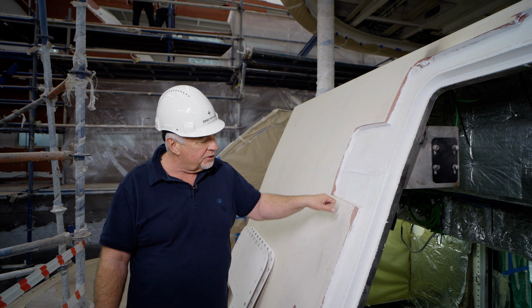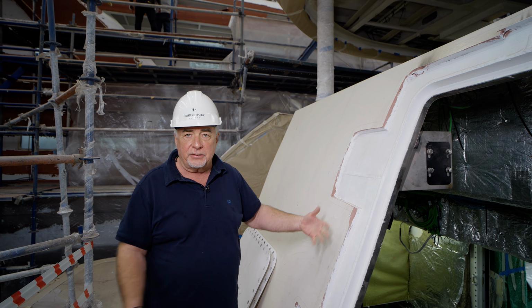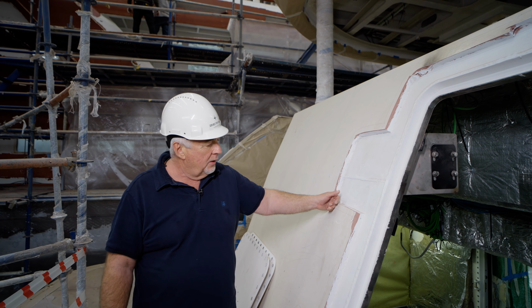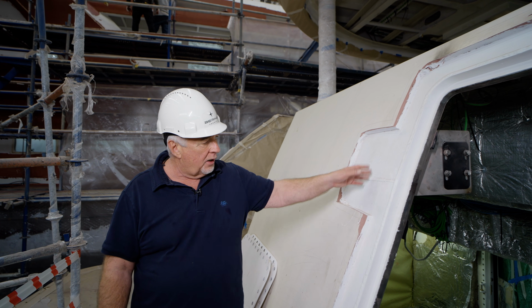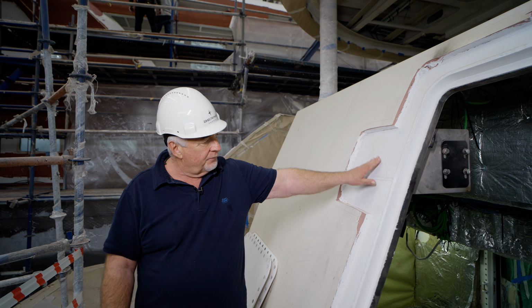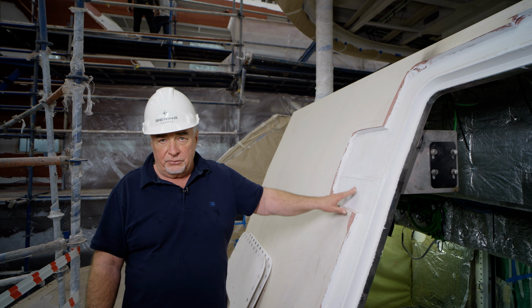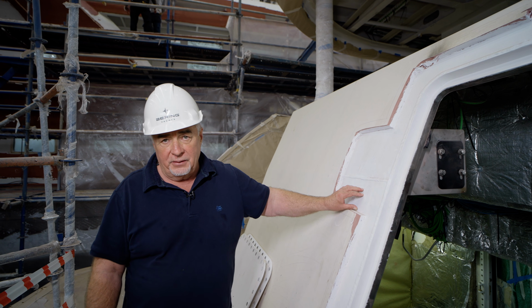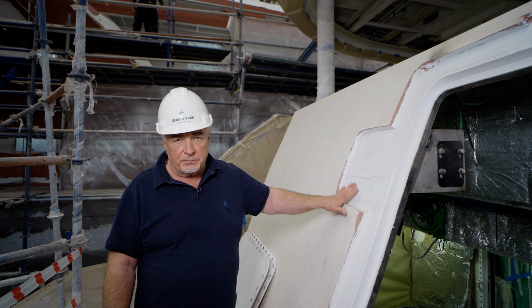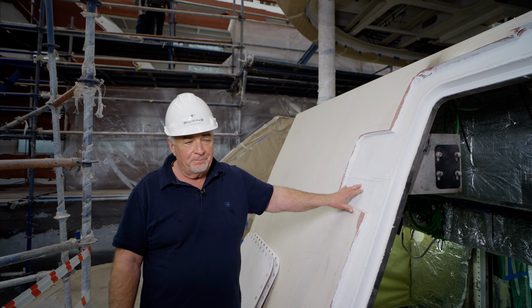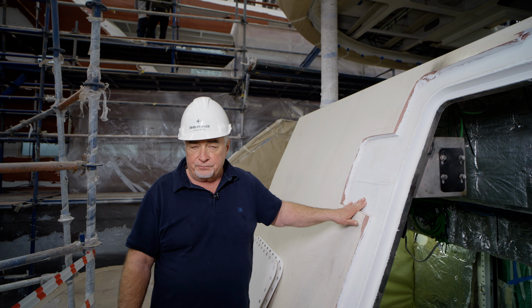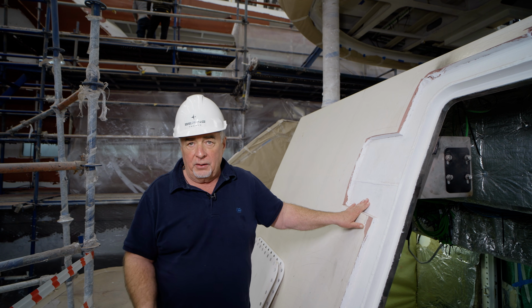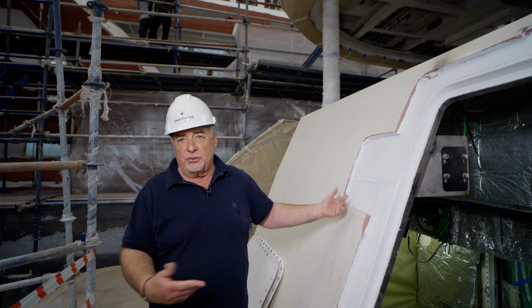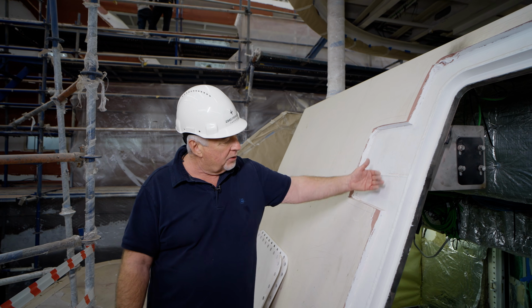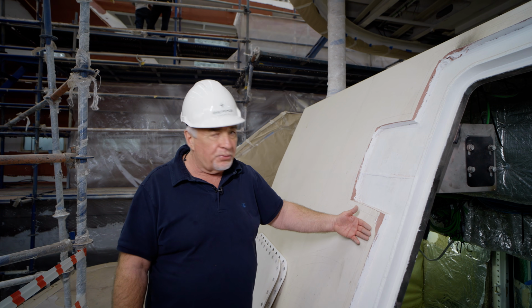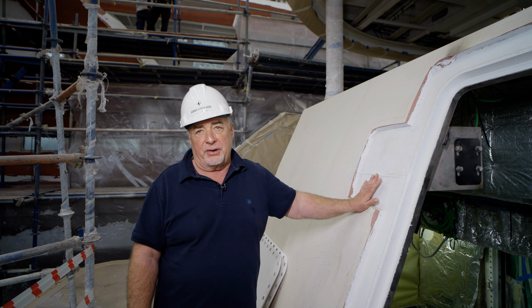However, if you damage this, let's say you bump into a concrete pole and it's crushed and you have steel exposed, you have to apply the protective primer. You have to put phosphoric acid to clean up whatever rust has already formed, and then you apply the protective primer, and then you're good to go until you get to the place where you can fix your fairing and apply all these layers, match it perfectly with the paint and repair it properly.